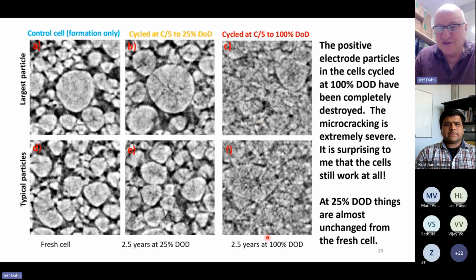But after 100% depth of discharge cycling for 2.5 years, you can see the particles are all cracked into pieces and almost completely destroyed. And this is because the volume changes of the particles are greater when the depth of discharge range is greater and the effect of microcracking gets more severe. And it's amazing that the cells even work at all after these 2.5 years at 100% DOD. So this again really shows you the importance of keeping the state of charge range that you're operating your cell small when you have these spherical NMC particles made of many, many primary particles.